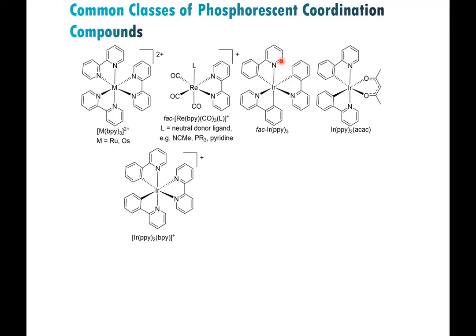And so there can be a few structure types that are common within these. So the homoleptic compounds, usually with the facial arrangement of the ligands being the one that's most thermodynamically stable, so the one that you'll typically observe and that has usually the best phosphorescence attributes. The heteroleptic compounds that are bis-cyclometalated, so 2 of the cyclometalating ligands and 1 of something else, often an acac, in the context of especially OLED compounds.